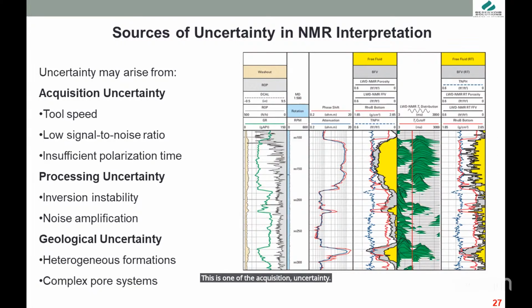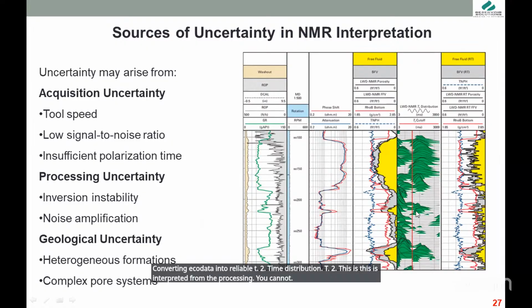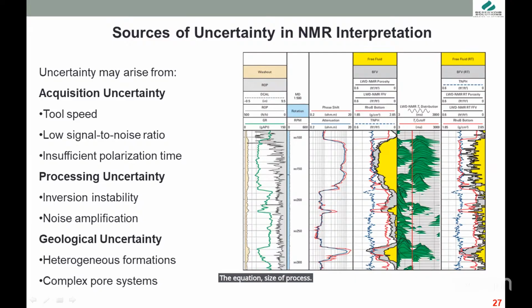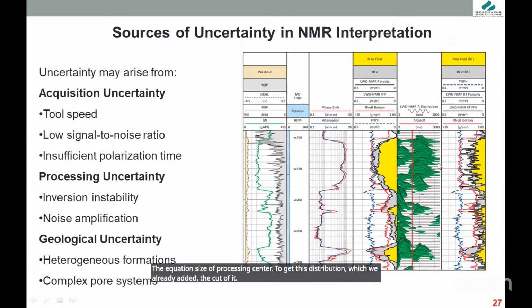The second source is the processing uncertainty, after you acquire the data and go to the processing center. Maybe you have a good acquisition, but the processing is not good. Converting echo data into a reliable T2 time distribution. T2 is interpreted from the processing. You cannot get it from the acquisition data. It's after the processing. It's the equation inside the processing center to get this distribution, to which we already added the cutoff for your estimation of your reservoir.